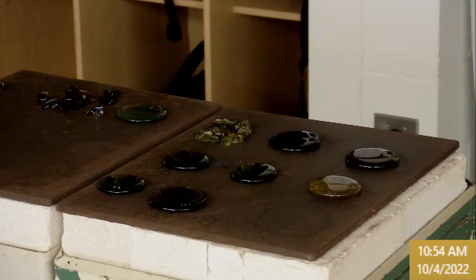A loader now gently pushes the bottles into what's called an annealing lehr. The bottles cool at a controlled rate as they move through the lehr. This gradually releases the stress from the glass. As the bottles exit, they're sprayed with lubricant. This enables them to move smoothly through the rest of the inspection and packaging line.